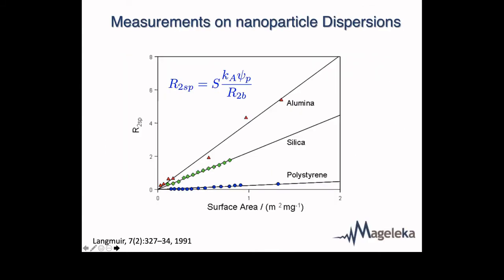So these are some not so recent data, but still nice data, looking at different particles and seeing how they affect the NMR relaxation time. So silica is one of the samples we've studied mostly. If you plot the R2SP against the surface area, we get a nice straight line. If you do it for alumina, now alumina obviously has aluminium atoms in the interface, and these interact differently with water magnetically. And so the effect for alumina is stronger than it is for silica.